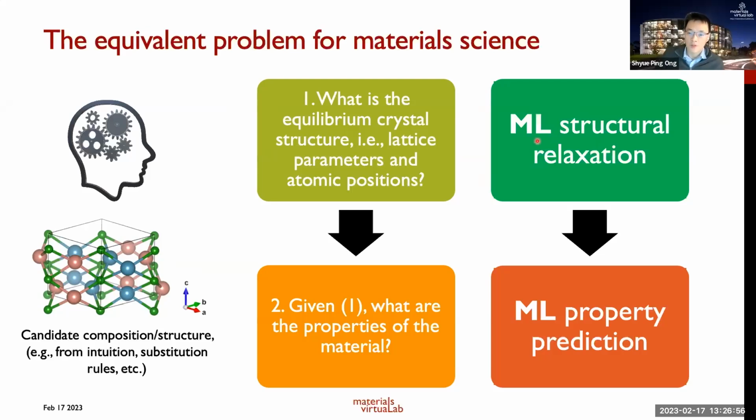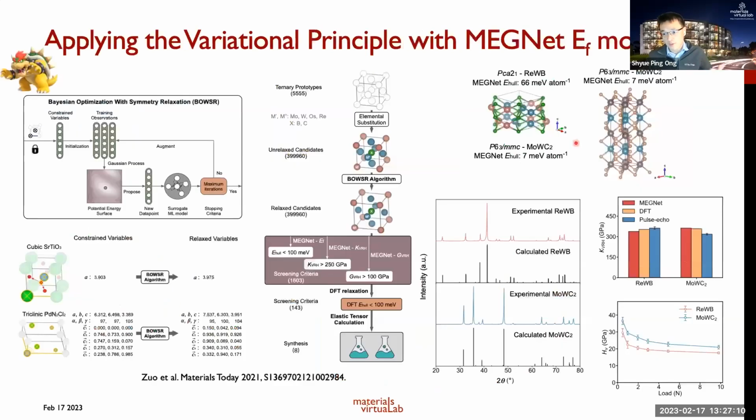And so in the past few years, my group has been focusing very extensively on how we use machine learning techniques to accelerate this portion of the materials design process, right? Now, one of the most naive ways you can do this, and it is still surprisingly effective, is to just use your energy models, right? So as I mentioned, we already can fit a MEGNet formation energy model that can predict the formation energy to within about 28 meV per atom, right?